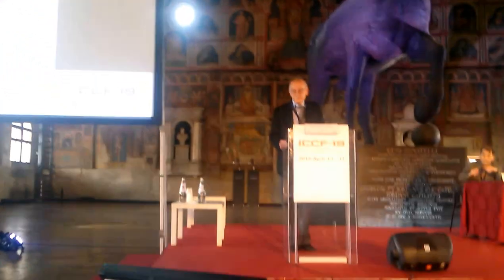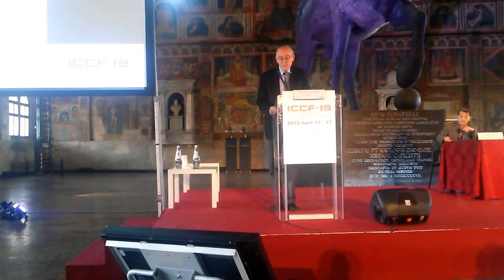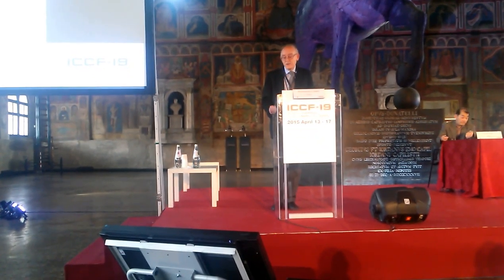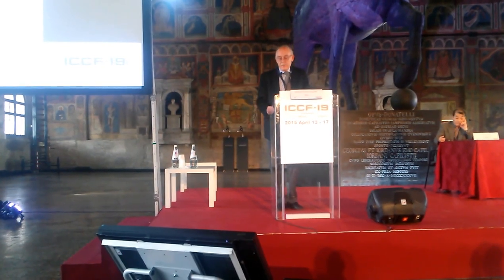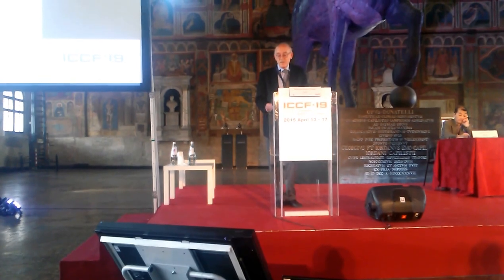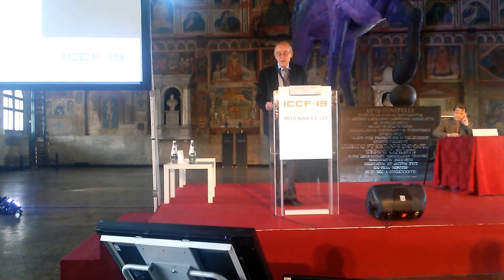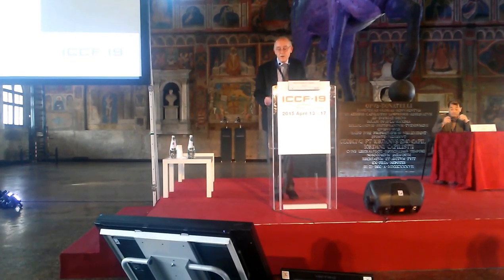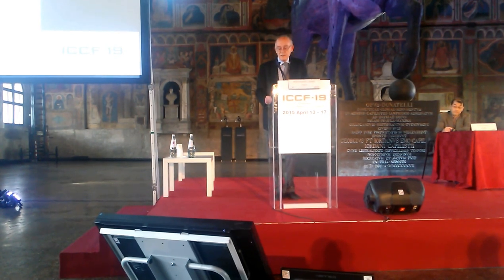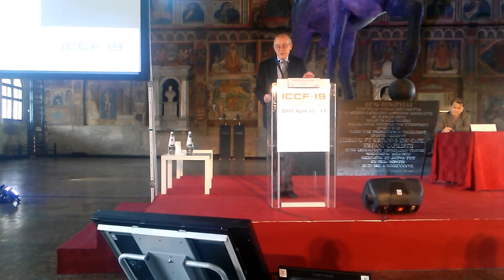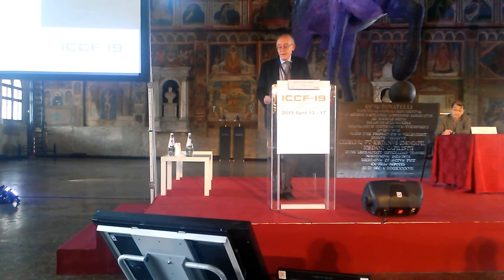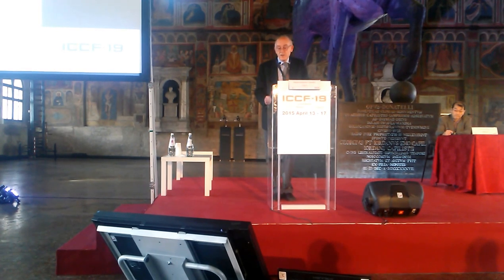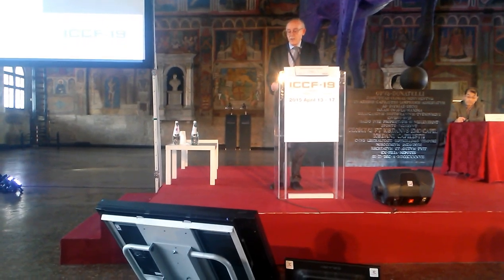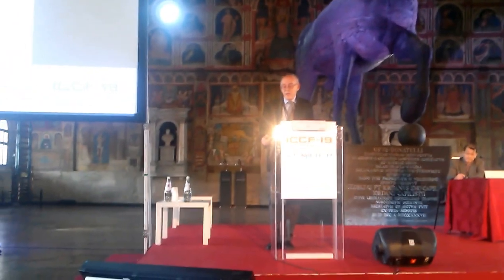Now let's go to my experiments. This is one of my reactors. I have six reactors in my lab. A couple of reactors are devoted to this kind of experiments. You can see in the bottom of the slide the sample used for helium neon stimulation is a chip, a rectangular chip, long 28 millimeters, 1 millimeter wide. The thickness of the palladium film is 250 nanometers. And we fill with hydrogen the reactor at a pressure of 1 bar and a half. And then we wait for 2 weeks.